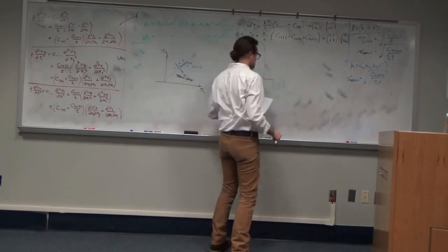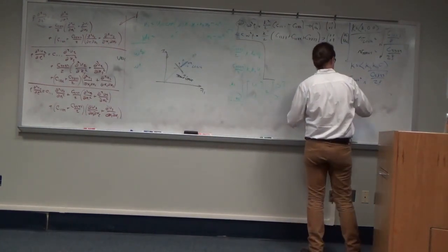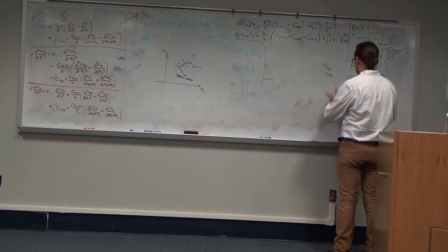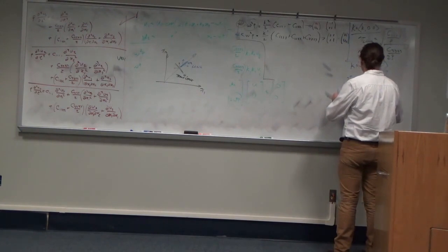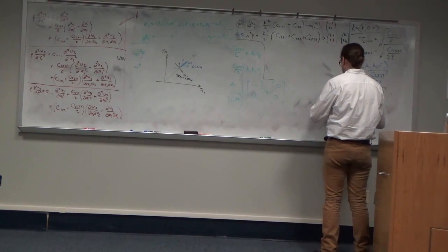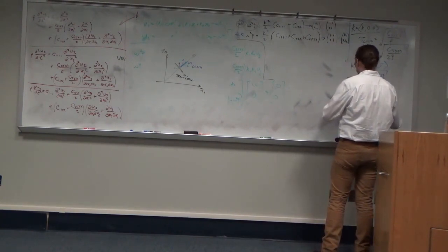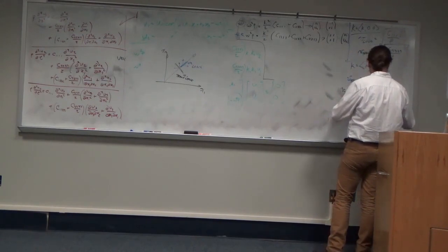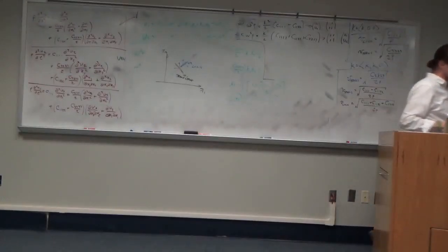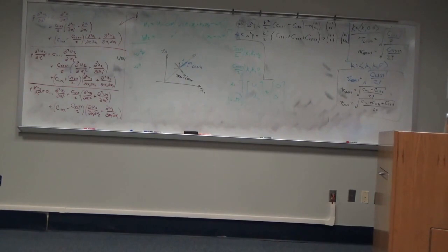And if we substitute, we get the transverse velocity is equal to the square root of c1111 minus c1122 over 2 rho, and the longitudinal is equal to the square root of c1111 plus c1122 plus c2323 over 2 rho. So the different wave modes have different velocities, and those velocities depend on the elastic constants. This is why if you're measuring the elastic constants, one thing you can do is you can use a transducer and a receiver and measure the waves propagating.